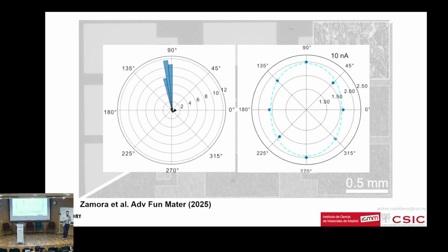If you do it without controlling, yes. But if you use the same tape, okay, you know that in this tape all the flakes are aligned along this direction, so you cut little pieces of tape and then you align them. But indeed, if you do it blindly, without taking care of how you place the tape on the substrate, it will average to 0, yes.